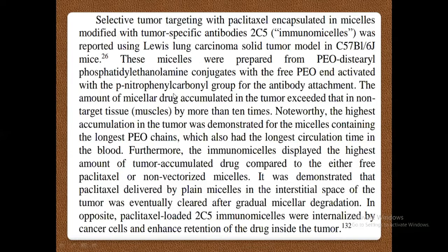The amount of micellar drug accumulated in the tumor exceeded that in non-target tissue by more than 10 times. The highest accumulation of this drug in the tumor was demonstrated for the micelles containing the longest polyethylene oxide PEO chains, which also had the longest circulation time in the blood. So when the circulation time in the blood increases, the drug will be reaching the target, and then it will attack the target.